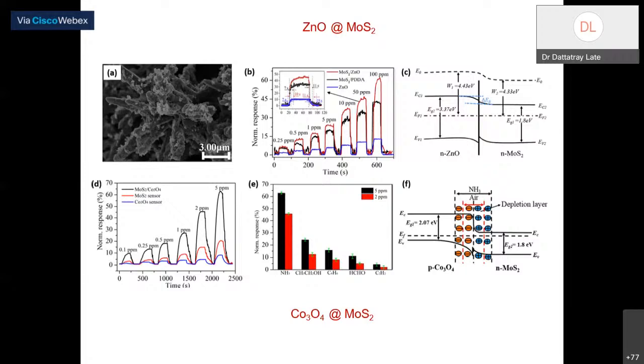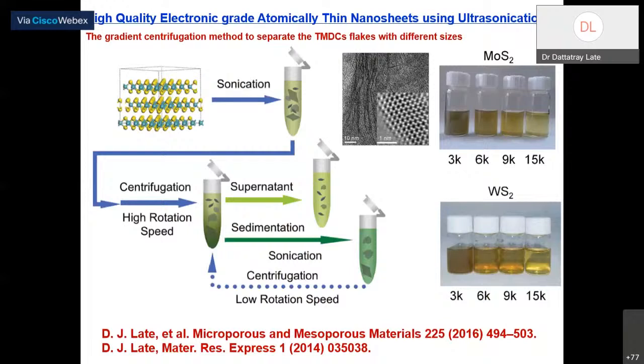And again, because of the depletion layer in MoS2, the band structure which we have found, and the other characterization, the characteristic feature, like I'm getting very high surface area, well designed, well aligned zinc oxide, which is giving very important properties, high surface area, and gives very high sensitivity. So traditionally, how can you synthesize this material in your laboratory?